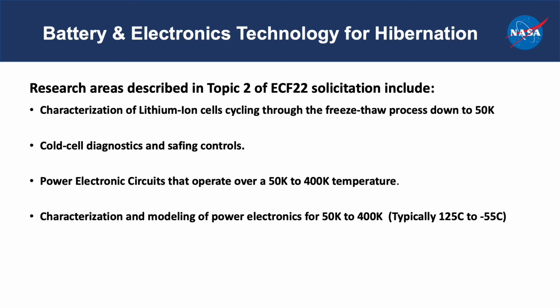We need to look at the electrochemistry effects and the thermomechanical effects that affect things like the jelly structure, seals, and built-in safety devices. From there, we also want to look at cold cell diagnostics and safety controls. We're looking at diagnostics to detect faults while the cells are still in a low energy state. We also want to have safety controls that may exploit the cold environment to slowly dissipate energy from a faulted cell and therefore prevent thermal runaway.